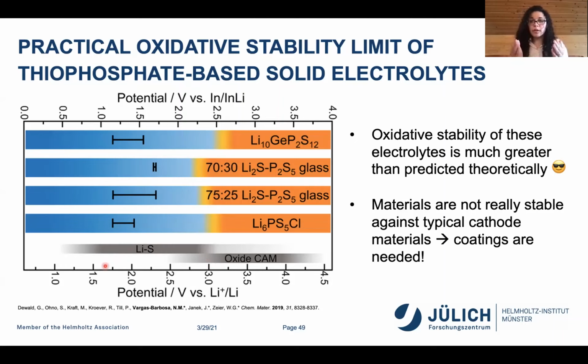But what is most important about our results is that the oxidative stability is actually far greater than what is predicted theoretically. This was critical, because if we had materials that were only going to be stable up to here, that's simply not going to be enough for applications. So we're very happy to be able to say that there is a practical oxidative stability of these systems. It depends slightly on the system, and it just needs to be studied carefully in order to be determined.